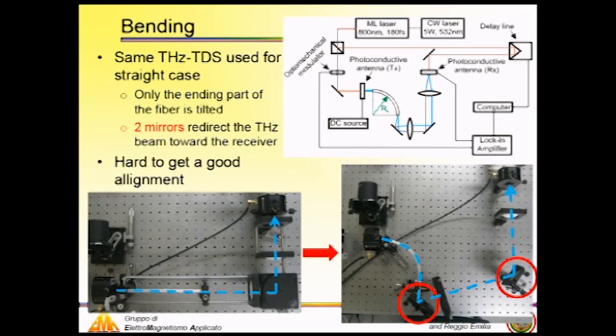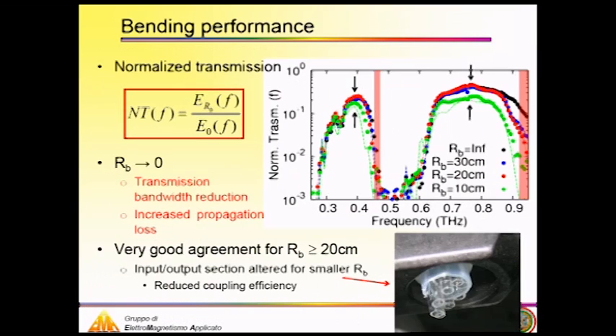The bending has been characterized using the same setup, but in this case, the receiver has been moved in order to form a 90-degree angle with the transmitter, as shown in this picture. And then to do the bending measurement, we tilted the end part of the fiber, and then through a couple of mirrors, we redirected it to the receiver. Well, it was not that easy to get a good alignment for the Terahertz radiation since it's not visible. However, here you can see a comparison between the numerical and experimental normalized transmission for our waveguide.